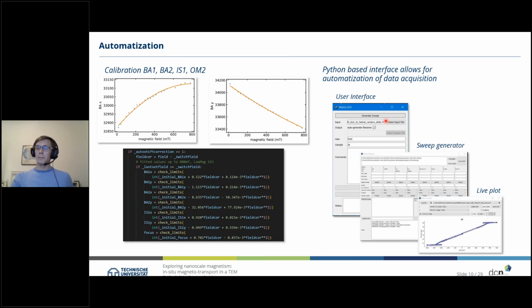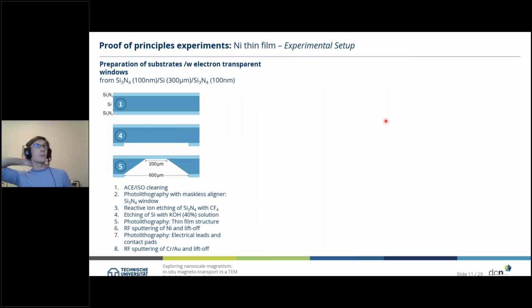Having all that set up, we started with a proof of principle experiment on a thin nickel film. To do so, we had to prepare our own E-chips to really have a nice hole setup. So we started with silicon nitride wafers, shown here in the image. Then we back etched the silicon nitride. We etched away the silicon with KOH.